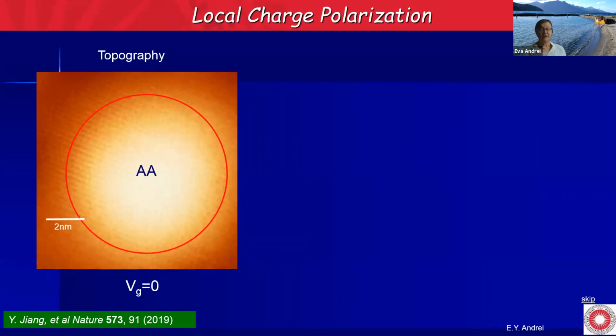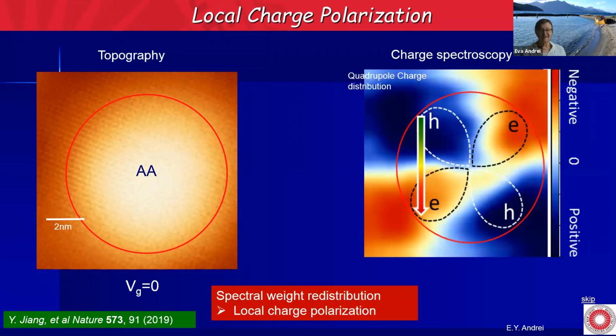Okay, so as I said, the spectral distribution between the full part and the empty part of the band changes with local doping. And here I have the topography, and this is mainly the AA region. This is sitting at charge neutrality. And then we take spectra at every point in this AA region and calculate the spectral weight redistribution at every point, which allows us to calculate the charge at every point. I'm not going to go into the details of this technique. This is a charge spectroscopy technique. If you're interested, I'm going to go through it in the question part, because it's going to take about 2 slides to do this. But the bottom line is that we are able to resolve the local charge within here.